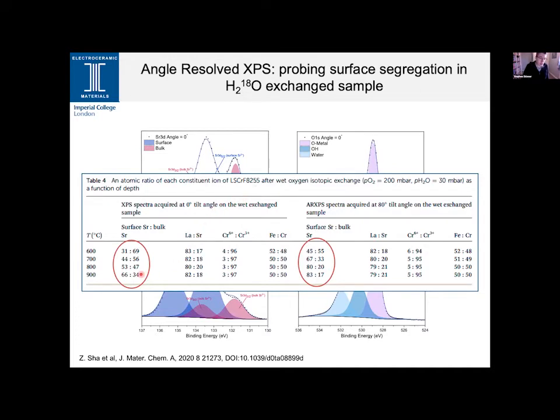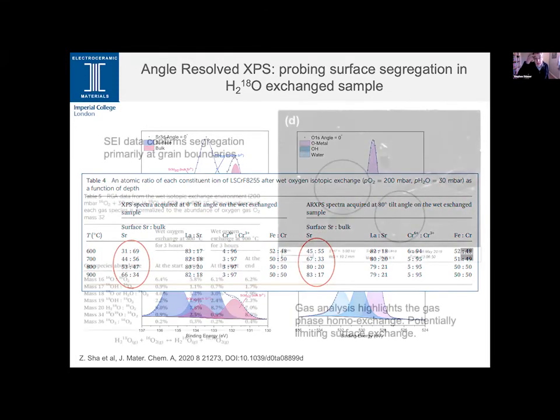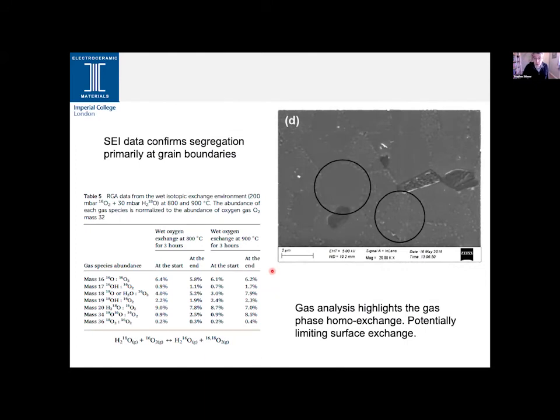of the depth. And if we focus on just the surface strontium to bulk strontium ratio, we can see clearly that as we go to higher temperatures, the ratios are significantly different between the normal measurements, so the penetrating, and the angle resolved measurement at the 80-degree tilt angle, so the shallow concentration, where we see significant surface strontium segregation. And notably, the cation species, the chromium species, are all staying roughly at the expected stoichiometries. So strontium segregation in these perovskites is perhaps not unexpected, and indeed that is confirmed by our secondary electron imaging.